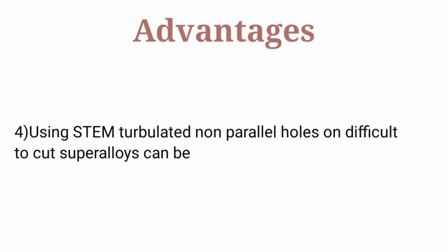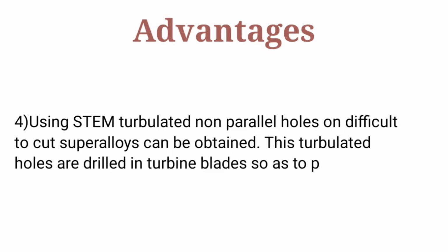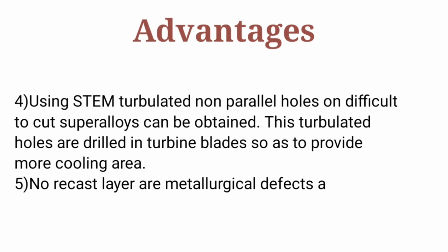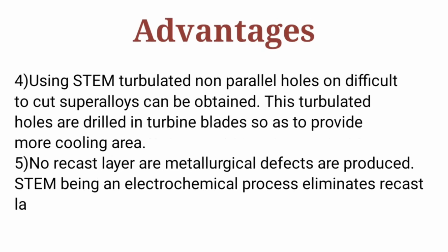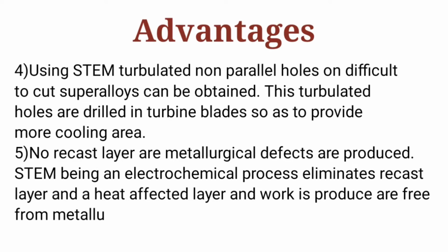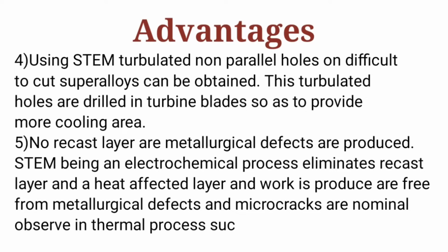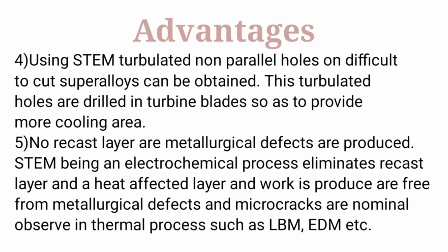Next, using STEM, turbulated non-parallel holes in difficult to cut superalloys can be obtained. These turbulated holes are drilled in turbine blades so as to provide more cooling area. No recast layer or metallurgical defects are produced. STEM being an electrochemical process eliminates the recast layer and heat affected layer, and work is produced free from metallurgical defects and micro cracks normally observed in thermal processes such as LBM, EDM, etc.